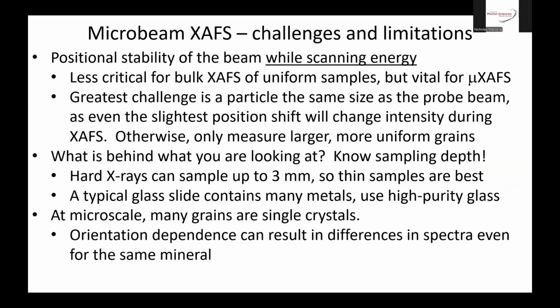So through these examples, we can identify a number of different challenges and limitations for microbeam XAFS. It's not that easy to get the microbeam to behave well enough to do XAFS. Most beamlines are optimized for imaging rather than energy scanning. So combining the two usually has some compromises and some challenges. The biggest challenge is the positional stability of the beam while scanning energy. Typically, the beam will want to walk a little bit on the sample during energy scanning. For bulk XAFS, where you have a uniform sample and a big beam, that doesn't really matter. But for microbeam, it's very challenging.